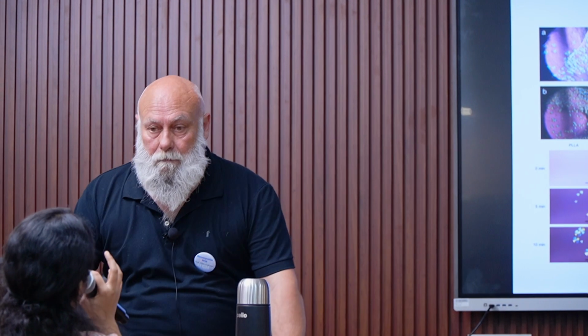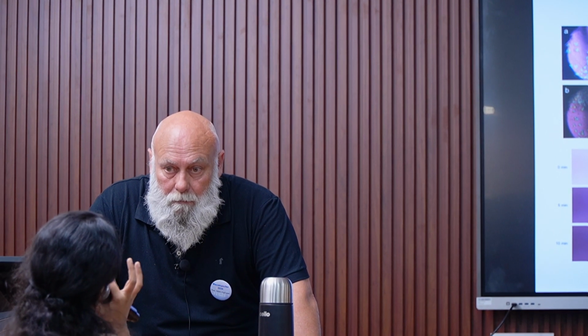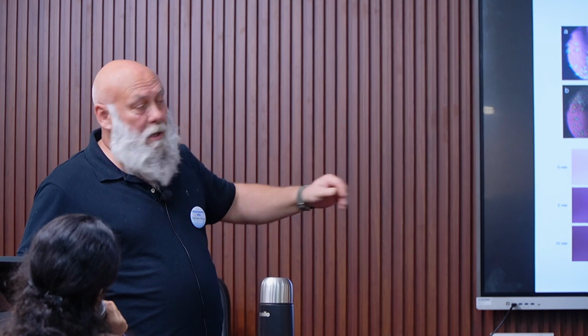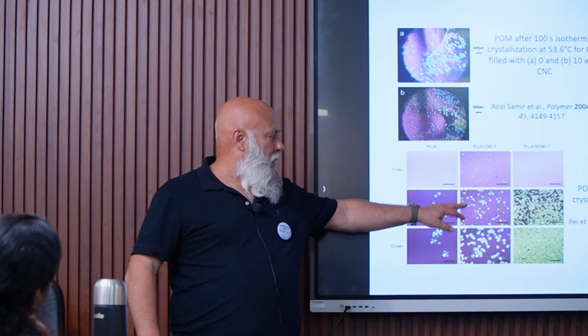Sir, is there any option to find out strain-induced crystallization through any imaging technique? So, you mean another imaging technique? Especially strain-induced crystallization. For strain-induced crystallization, usually we record the X-ray diffraction pattern during the test, and so we can see the emergence of crystallization peaks. So XRD coupled with tensile testing. Exactly. After that, maybe you can have an idea, but it's not so clear as here.